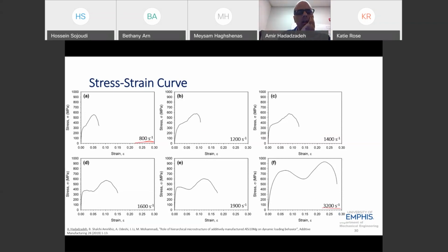The top graph shows the material behavior under high strain rate deformation. In these three cases, 800, 1200, 1400 per second, we see an initial hardening in the material up to a peak flow stress. Here is the peak flow stress. And then after that, once we stop the test, we have a softening. This softening is not related to the behavior of the material. This softening is due to the reduction in the strain rate because we deform the material and we stop it. So during deceleration of the bars, we have such a drop in the stress.